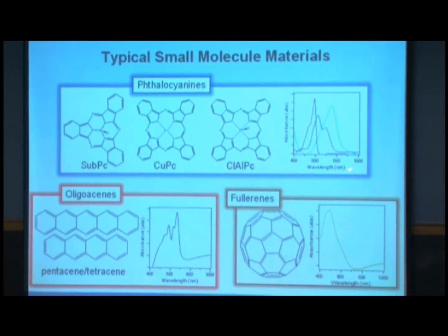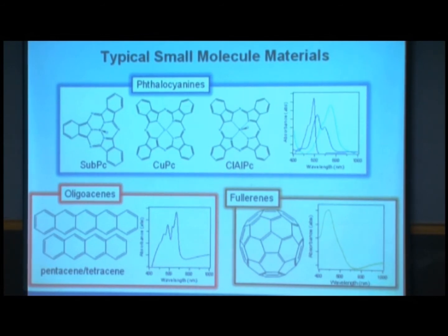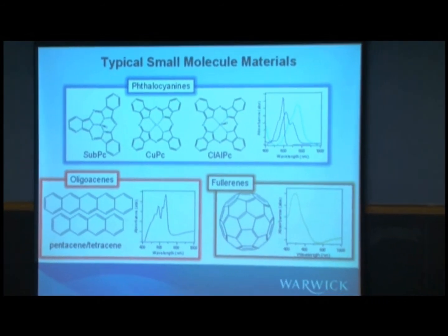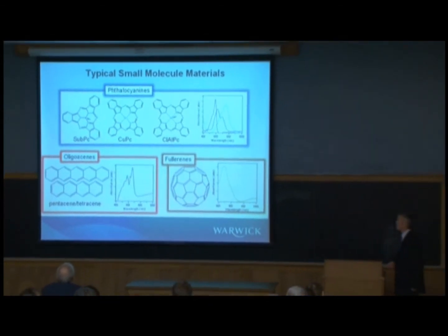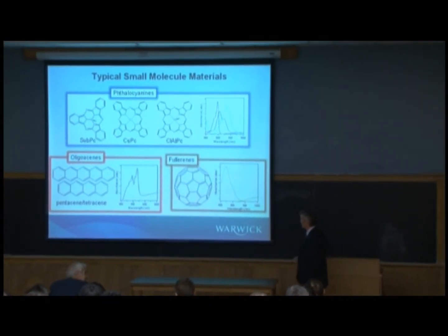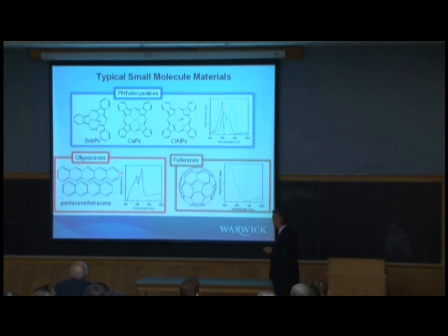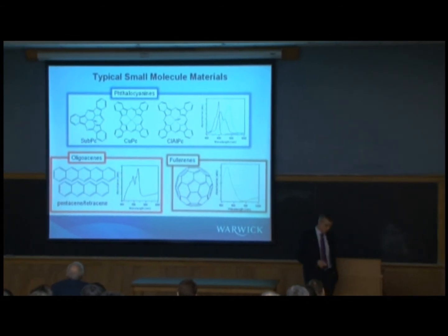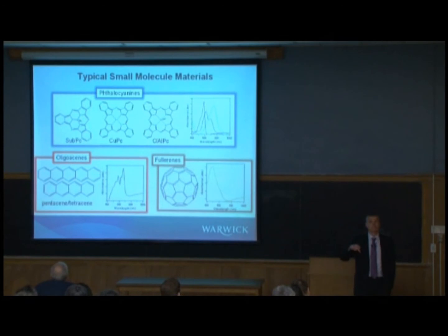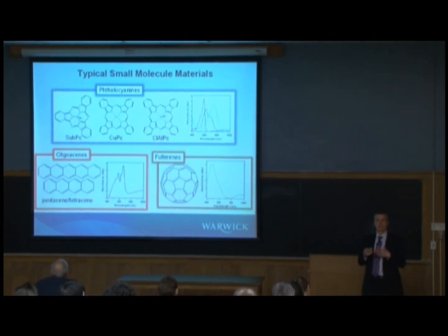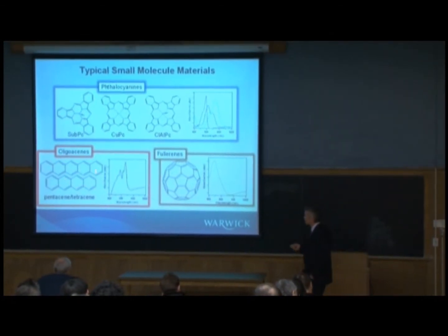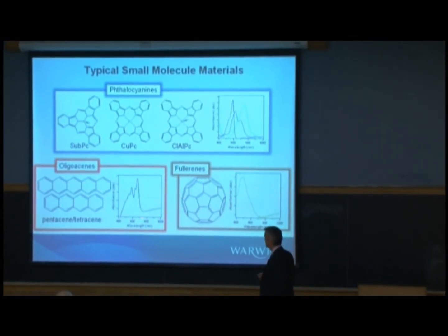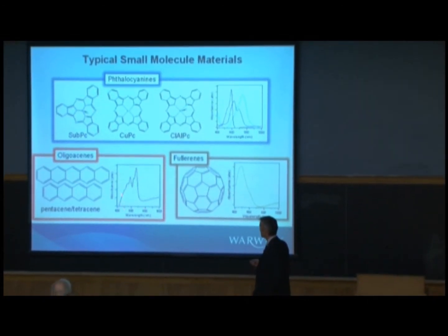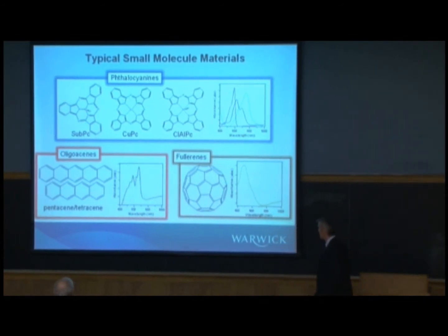So these materials absorb broadly in this regime from about 500 up to about 900 nanometers, depending on the particular choice of material. These are commercially available materials, but clearly you can do different things with those materials to change the properties. Oligoacenes, things like pentacene and tetracene, are also good materials, and in fact these materials are used quite a lot in organic transistors. They tend to pack in a semi-crystalline way, so you get good charge mobilities in these materials, and again, these absorb somewhere in the 500 to 800 nanometer regime.